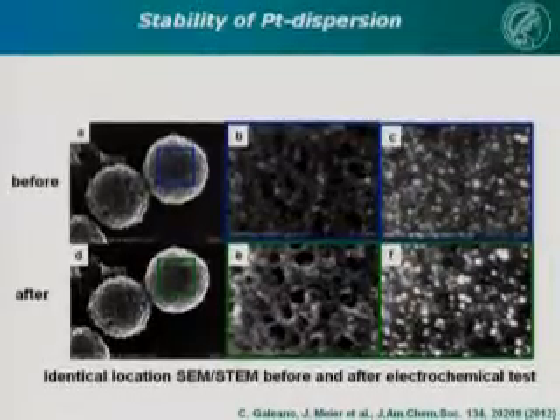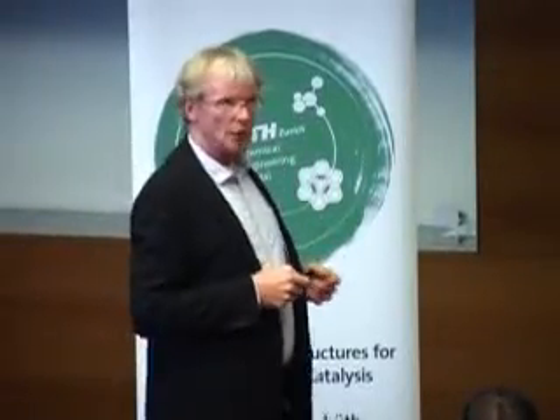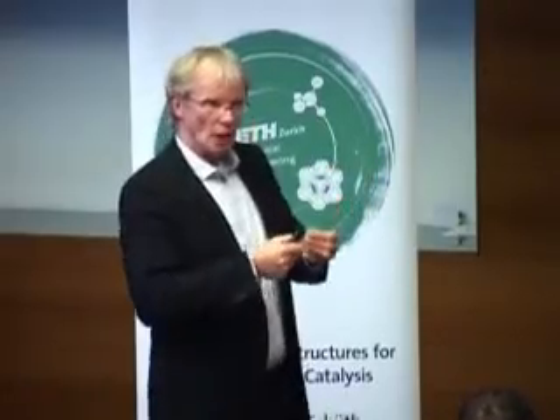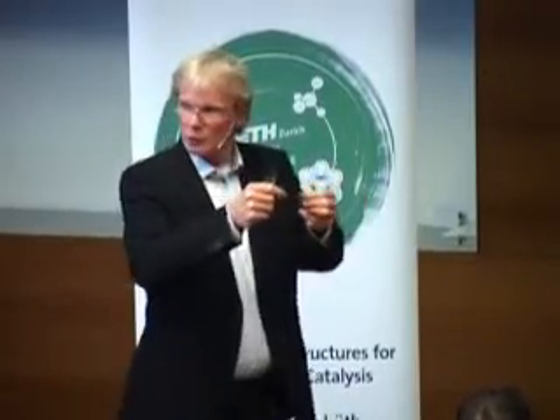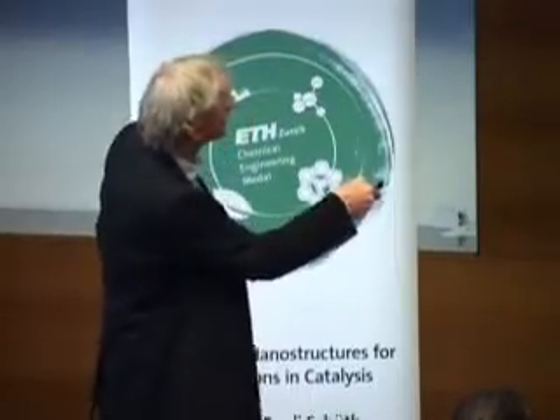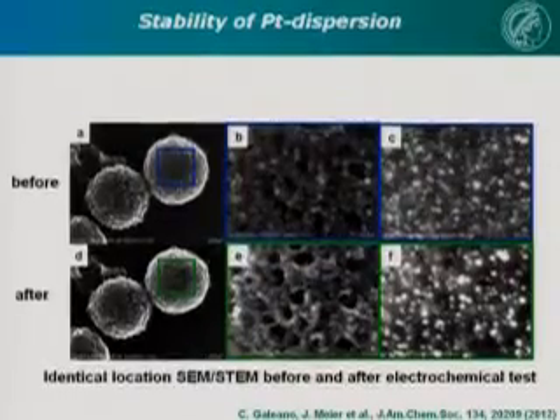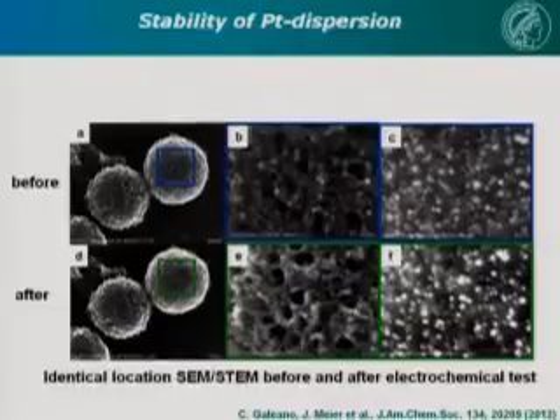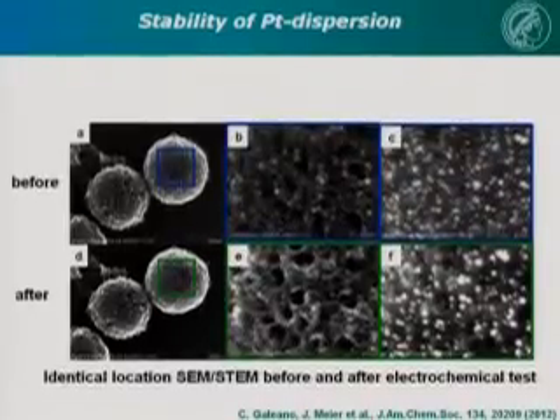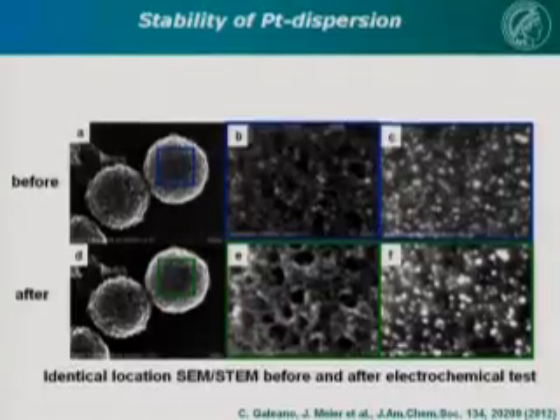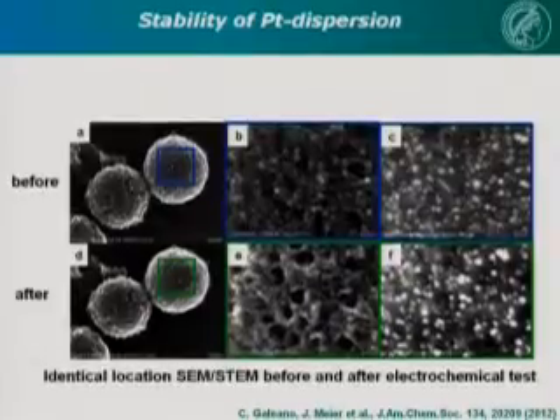Then you put it on an electrode, put it in a rotating disk setup to do the electrocatalytic experiment. You take the grid out again. Since it has a coordinate system, you can find the same location again. And you see here are the two spheres again after the catalysis, exactly the same location, and then analyzed. And what you see is actually quite interesting. The number of particles, the size of the particles has not much decreased or changed. I'll show you quantitatively later. But actually the structure of the support has to some extent been changed.